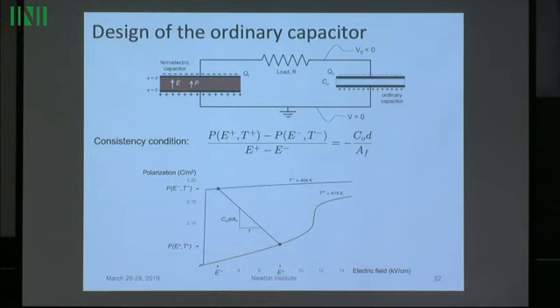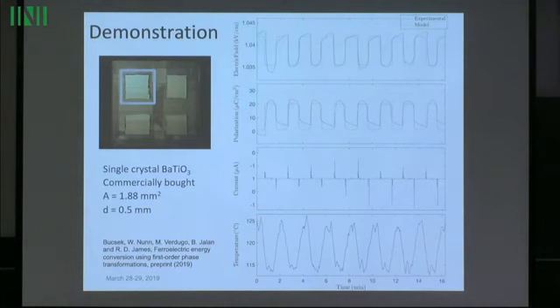If we want as big a change in polarization as possible, of course we should make the slope of this line as steep as possible. We should make a huge capacitance for the ordinary capacitor. You want to make that as large as possible. So this is D over A. There are many choices of the C0. So that's what one should think.